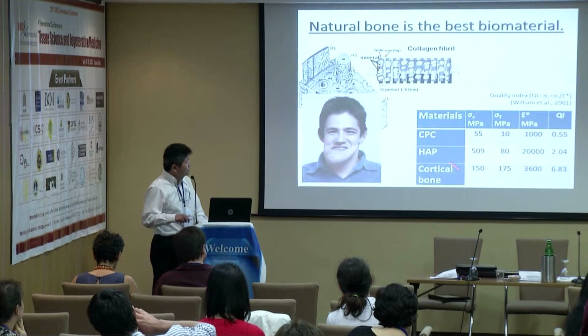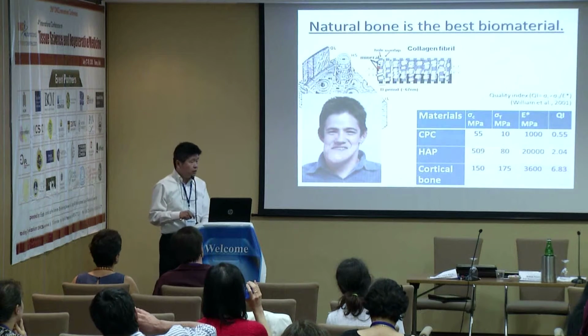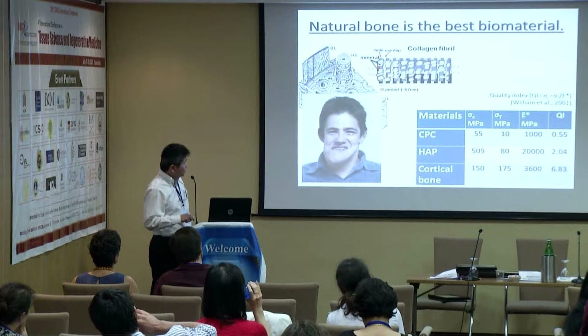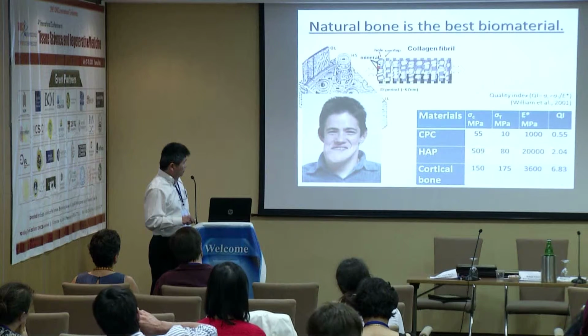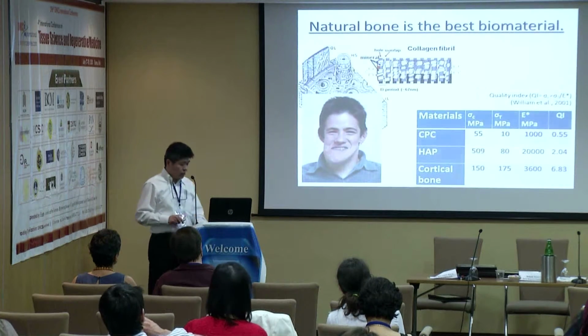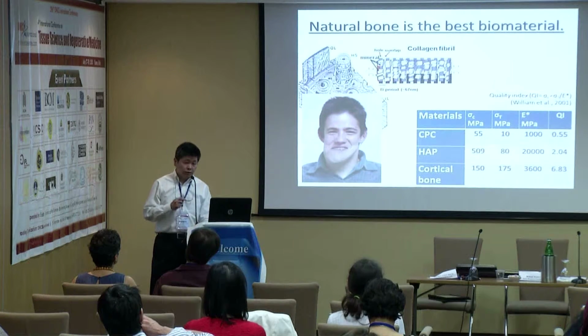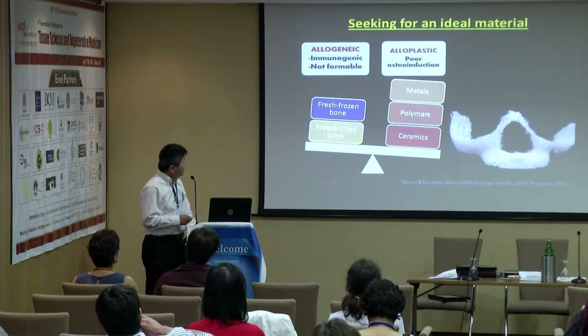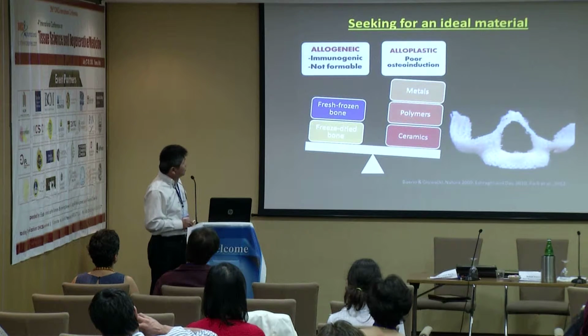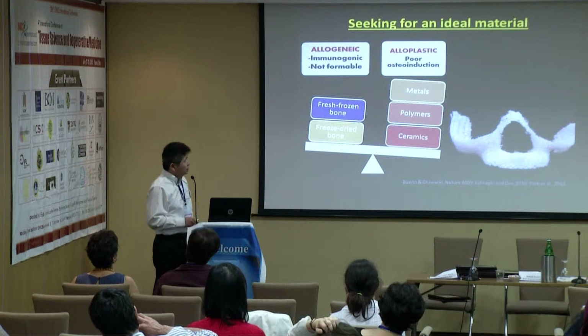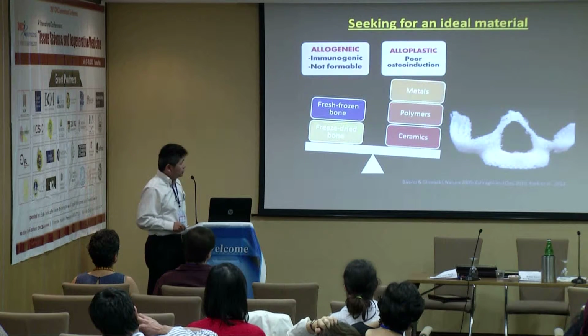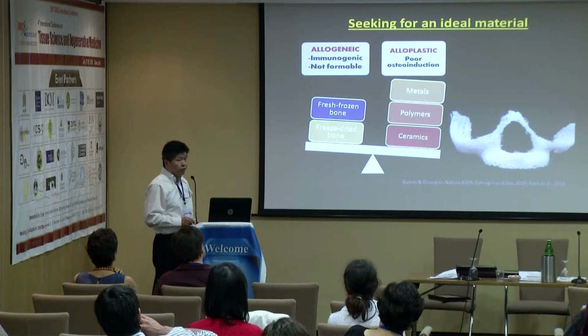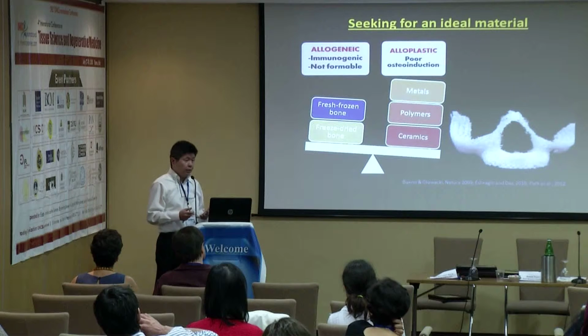This shows that even with natural bone, if you put it into the wrong spot and it still has some growth left, problems occur. This patient underwent surgery for joint replacement. However, 10 years after that procedure, the rib continued to grow and became asymmetric. So even with the best material, we still have issues, and there is a need to develop new materials. There are two options: one is using organic material, which has immune issues, and the other is using alloplastic synthetic materials. In this area, many people have pursued different approaches. Metallic materials are generally used, but they are not resorbable and cannot be used long-term.